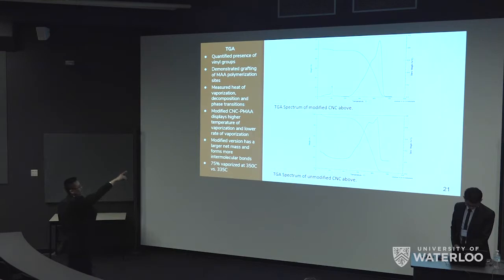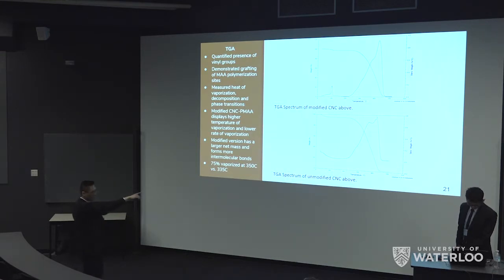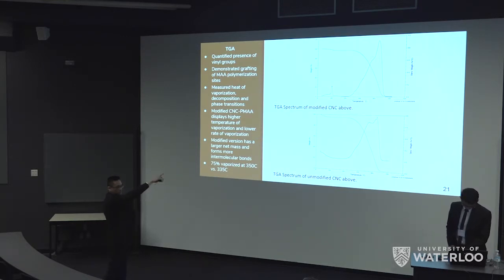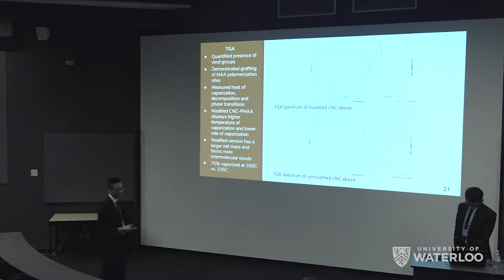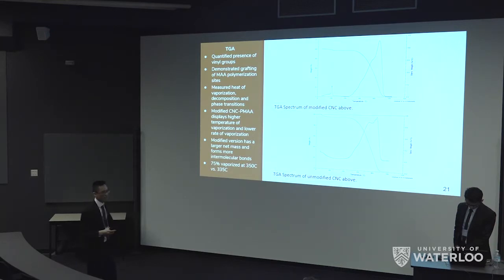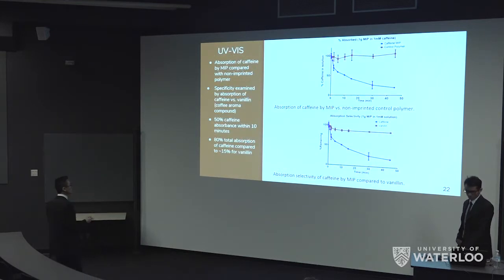Furthermore, the blue curve represents the derivative of the weight percent as a function of temperature. In the second plot, you see two peaks as opposed to one peak for the first. The two peaks correspond to the poly-MAA and the CNC separately, and the second peak confirms that it is covalently bonded. So we now know how the components are bonded together.